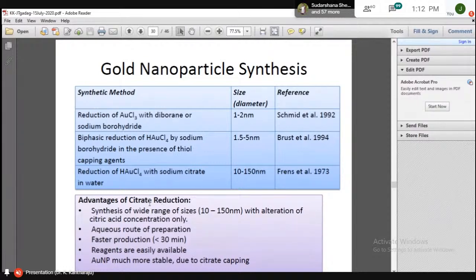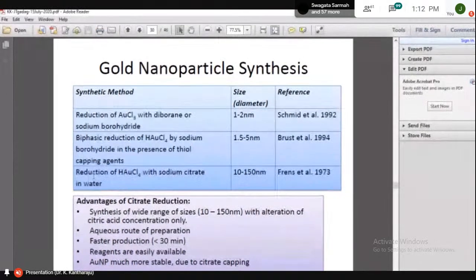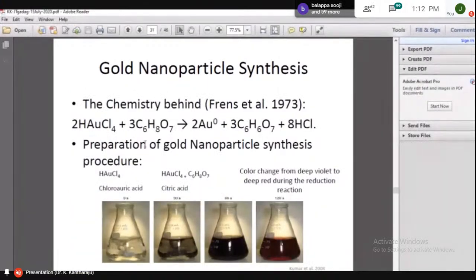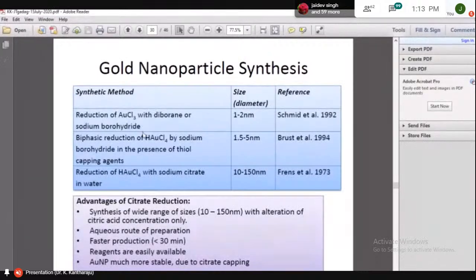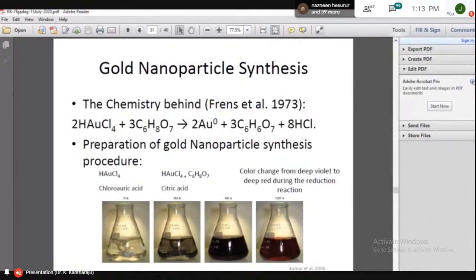So we looked at the literature and saw a very simple method, because we can't go for exhaustive methods in the biochemistry lab: just a simple sodium citrate in water method, developed by Frens et al. We adopted the same protocol for making gold nanoparticles using auric chloride, or chloroauric acid. In the previous talk, my colleague Manjana showed nanoparticle preparation by oxidative and reductive methods, with many acids: citric, ascorbic, oxalic, and more. Here sodium citrate worked fantastically.